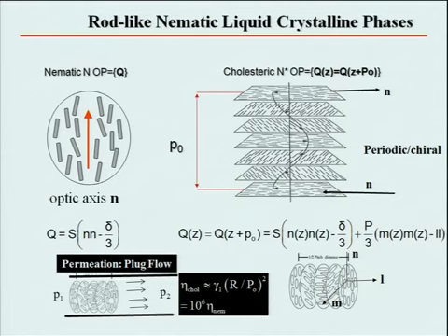So here we have an orientational order fluid. It has no positional order, is an anisotropic viscoelastic material characterized by an optic axis. So the simplest description of this system is the Q tensor quadrupolar order parameter that is composed of two parts. One is the scalar order parameter that changes with concentration for lyotropics and temperature for thermotropes.